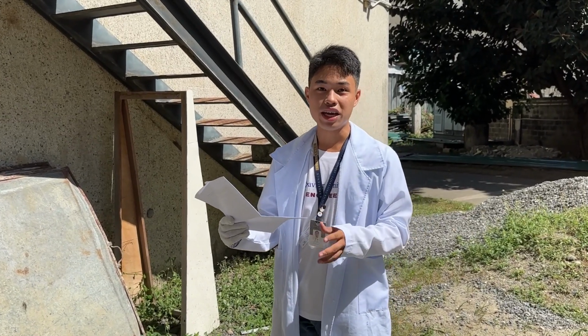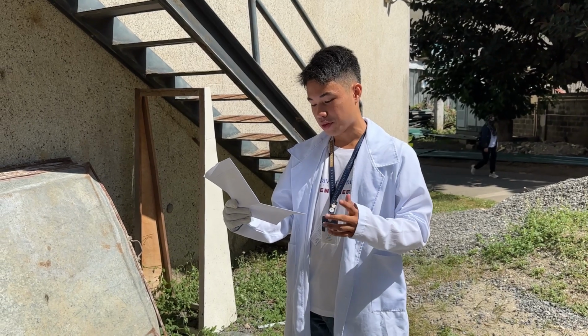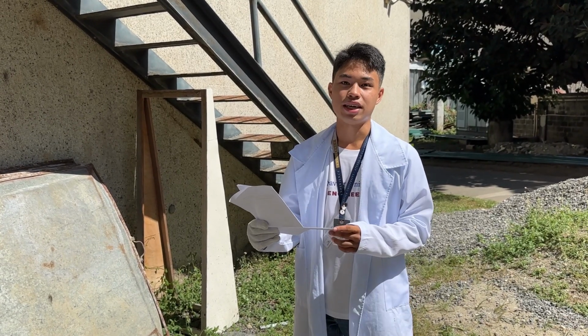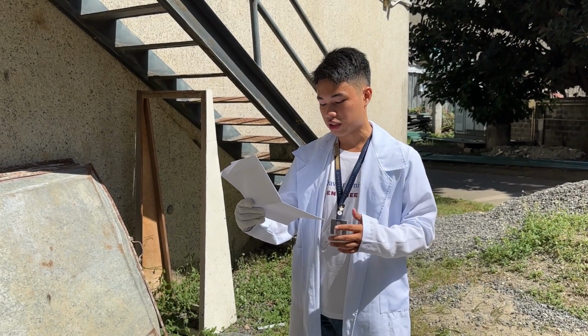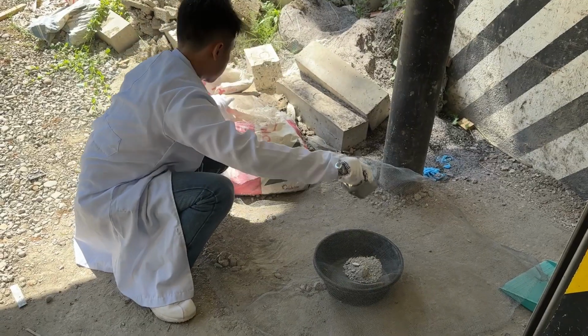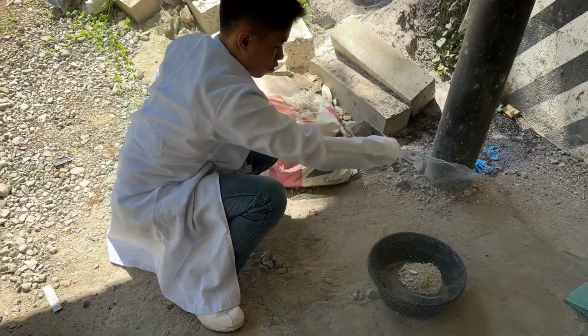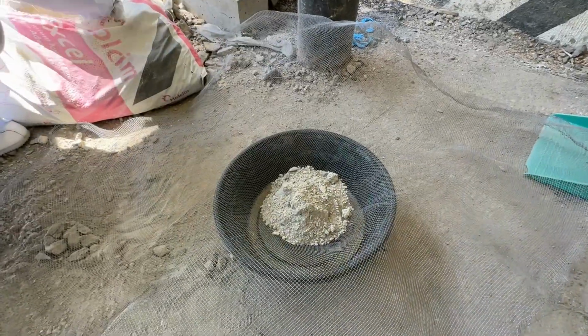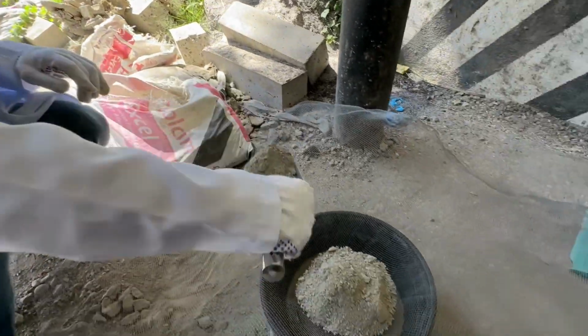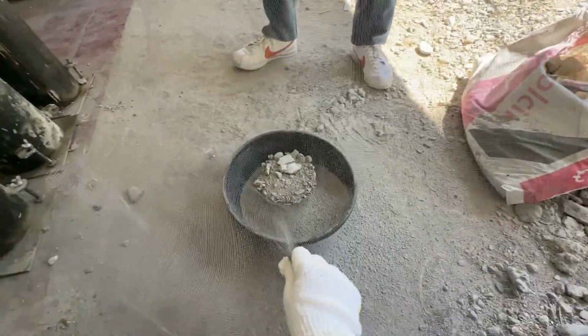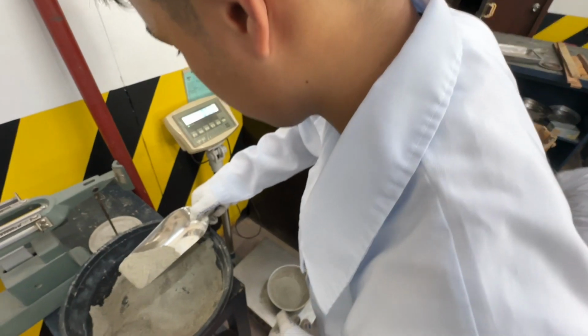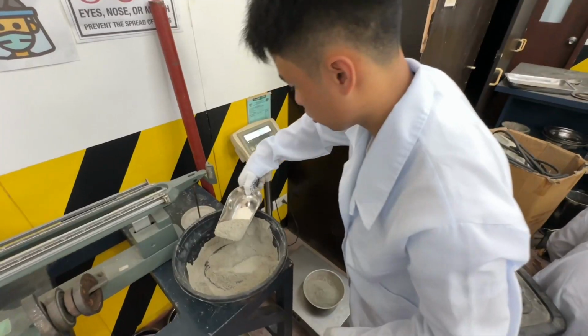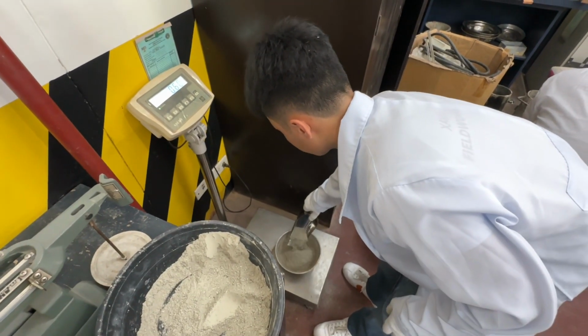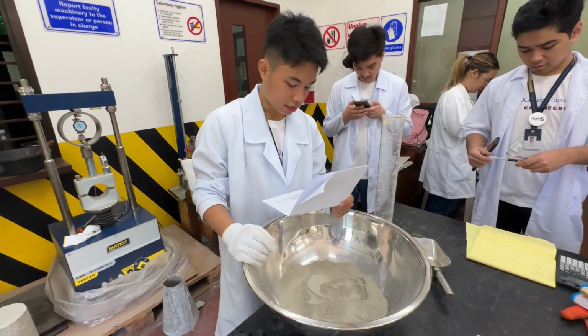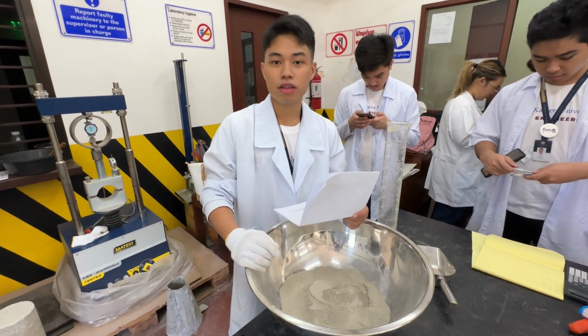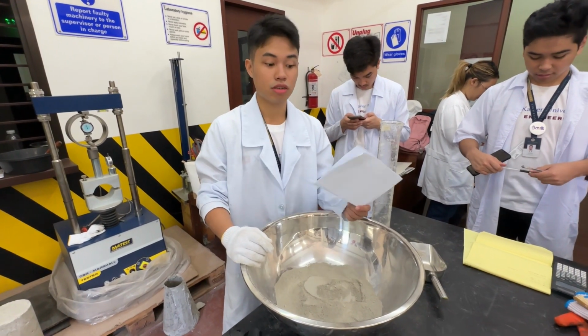To start, we need to prepare the specimen needed for the experiment. We will then need to sieve the cement until acquiring 650 grams for sample testing. Then we will use 170 milliliters of water and pour it into the cement mixture. Now that we have obtained 650 grams of cement mixture for the sample test, we will now pour 170 ml of water to the mixture.